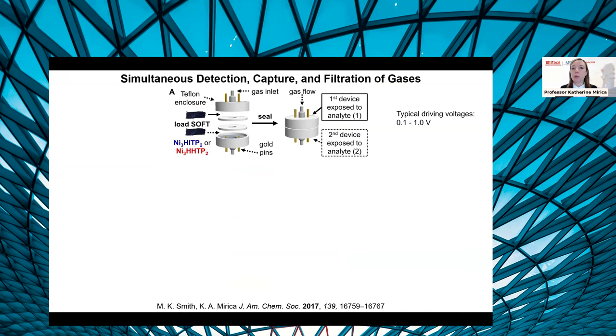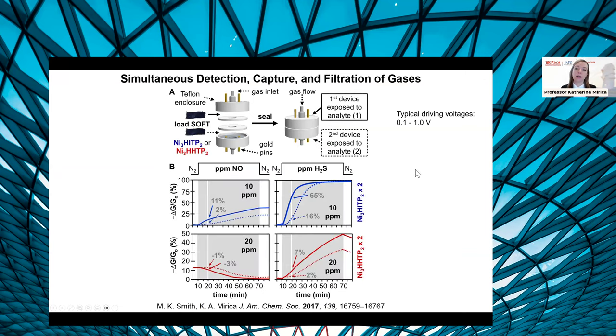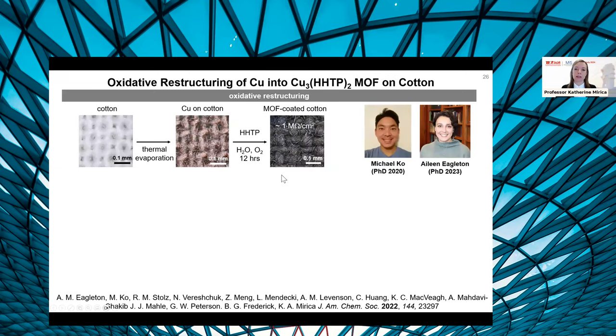So for example, if we put two devices in series and then flow the gas stream through that device assembly, we can demonstrate that the response of the second sensor is attenuated by the presence of the first. So the first sensor begins responding right away upon encountering this gas. That's the solid line in these data plots that I'm showing. But the onset of the response of the second sensor is delayed because the first sensor is not just sensing the analyte, but it's uptaking it, filtering it, and only permits it to go through once some breakthrough capacity has been reached. And so that can be qualitatively demonstrated by putting these devices in series.